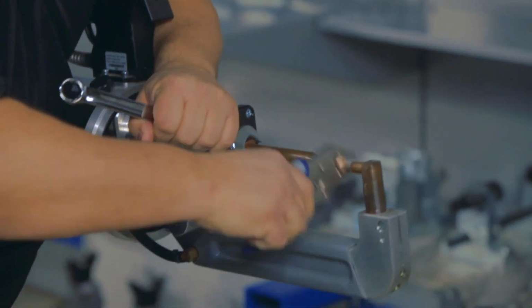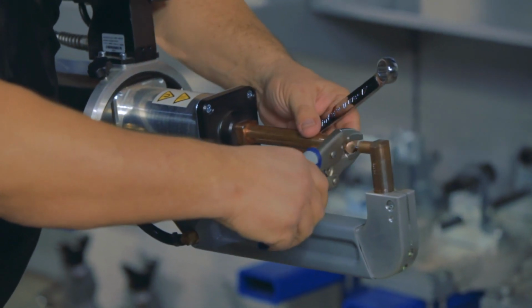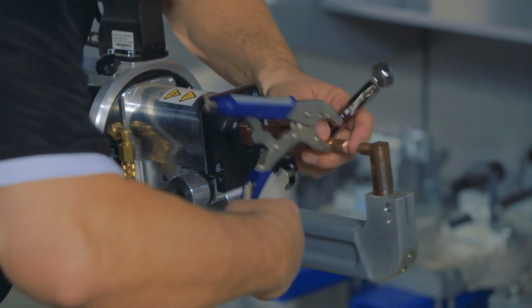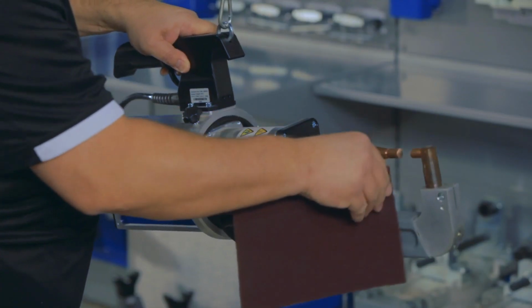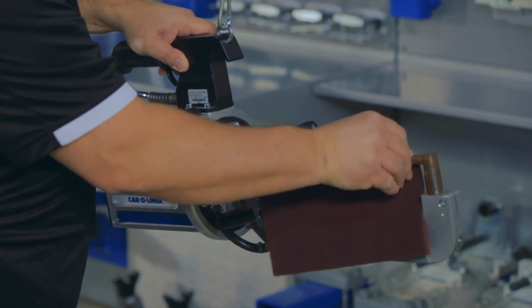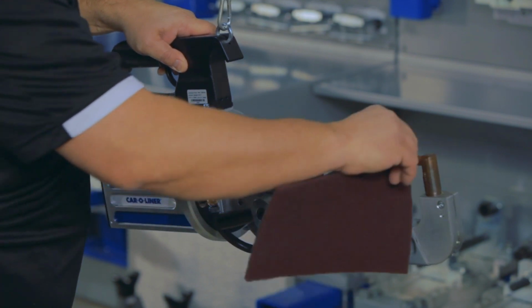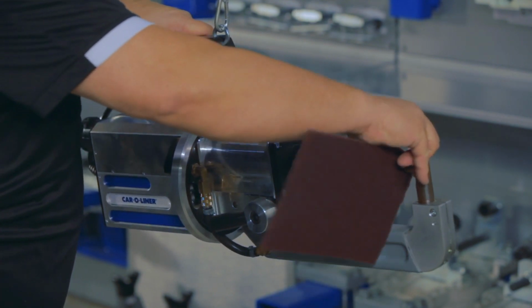So it's very important to stress tip maintenance, making sure that if you've got a cap such as this, that they're being replaced when they start getting some material on the tip itself, or if it gets that mushroom effect. Very important to make sure that we're maintaining our spot welding tips, because even if we've got the proper squeeze pressure and the proper amperage, we will not get the same type of weld as that head continues to mushroom. So very, very important to make sure that we're doing that.